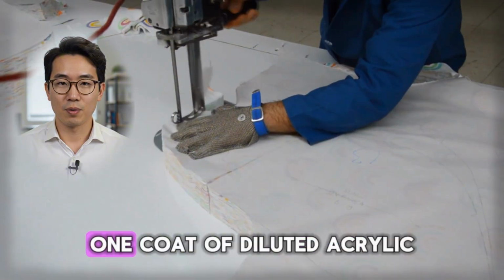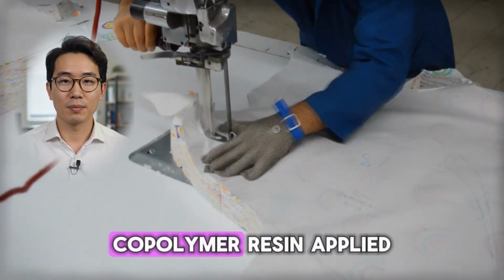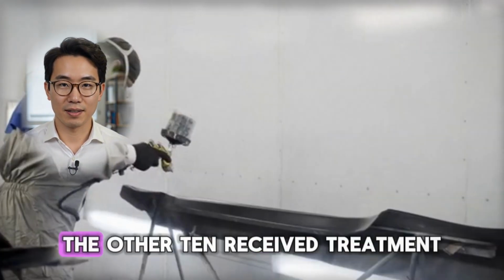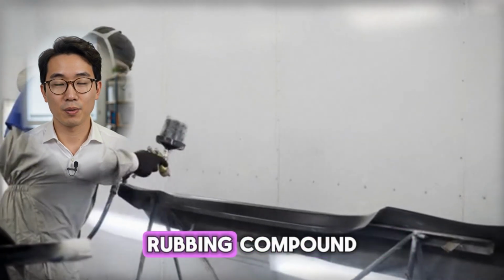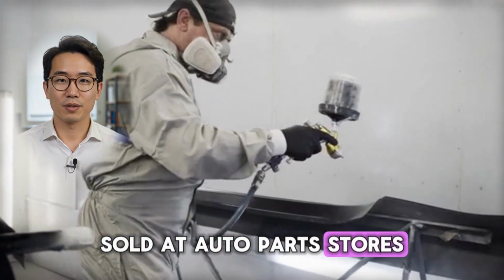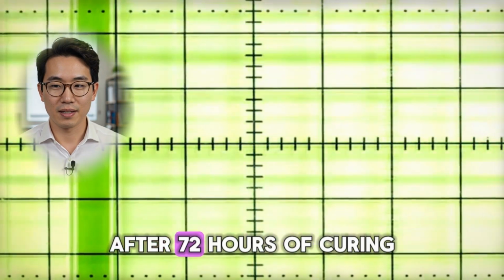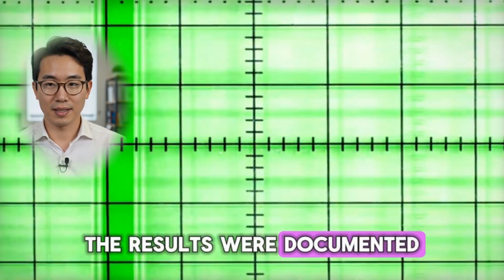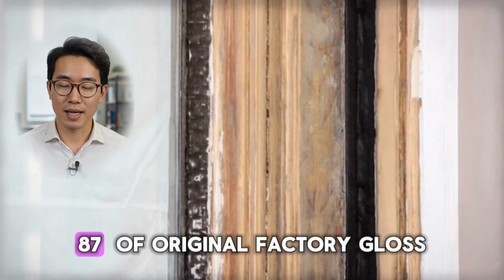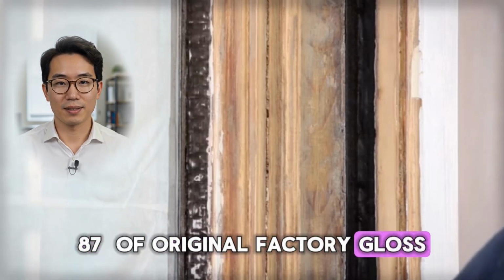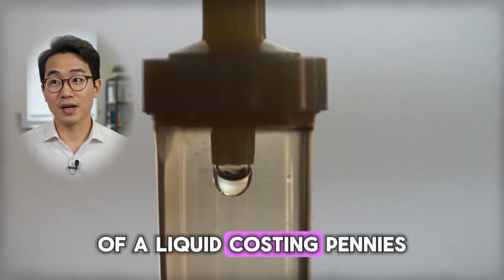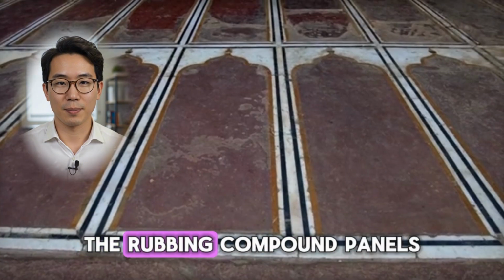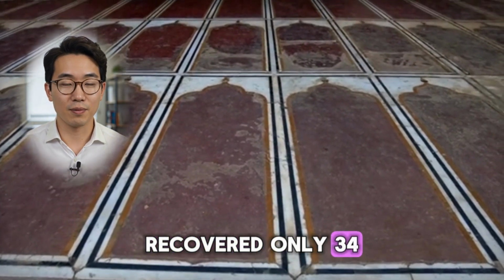10 panels received 1 coat of diluted acrylic copolymer resin applied with a foam pad. The other 10 received treatment with a leading commercial rubbing compound sold at auto parts stores across the country. After 72 hours of curing, the results were documented. The resin-treated panels recovered 87% of original factory gloss from a single coat of liquid costing pennies per square foot. The rubbing compound panels recovered only 34%.